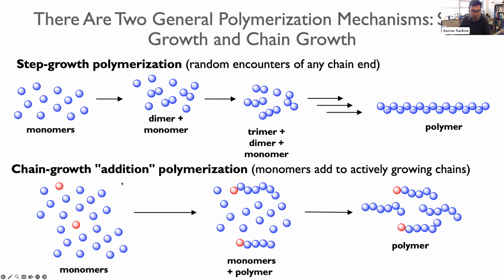That's the chain addition or chain growth polymerization, where you have a site or a few sites that are active and monomers keep adding to that site. So in the course of those polymerizations, you have monomers and you have long chains and very few species in between. So that's how polyolefins are made. We have, say, the Ziegler catalysts, where you have active sites and you keep adding ethylene. And so the active chains grow, the inactive chains don't grow, and then you have a lot of ethylene around.